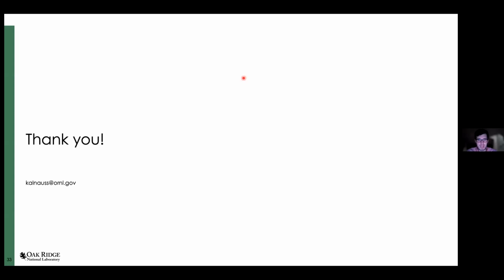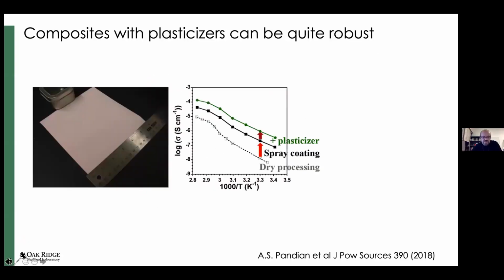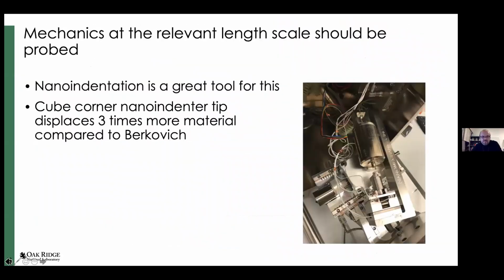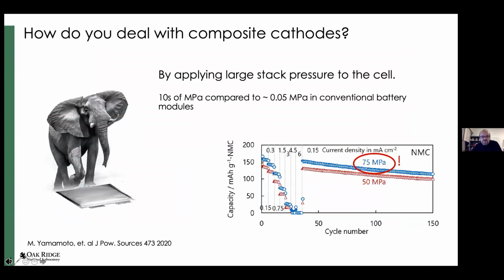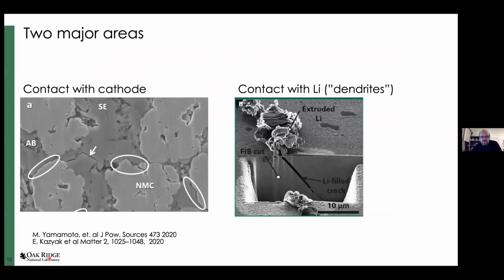So that's probably a good transition to Marcus' question. Could you comment on the need for pressure in the solid state cells? I think you had a brief slide or a brief discussion on it at the beginning, but if you could go back to that. Yeah, that's just a simple brute force to keep all the interfaces together. Because these cracks appear, you have dimensional changes in the active particles of your material. And imagine the same thing happening on the negative electrode side if you use silicon, which can deform to hundreds of percent of strain. So these cracks will appear, and this is where the contact will be lost.